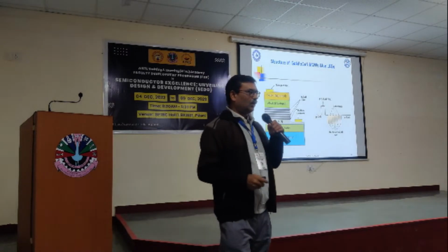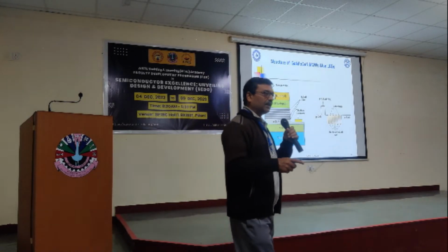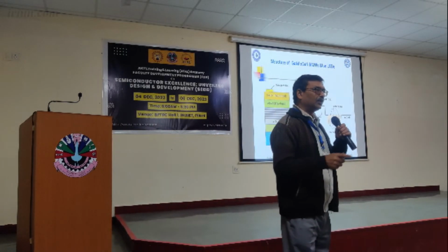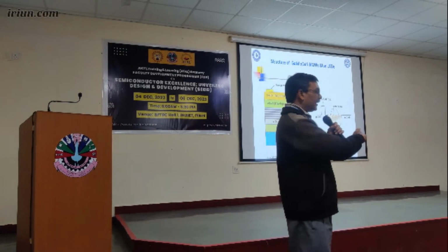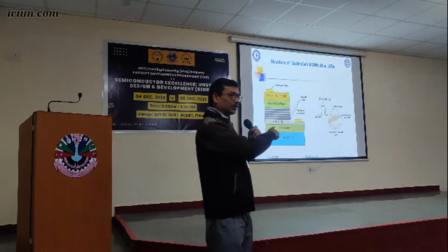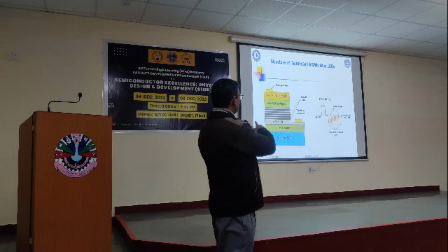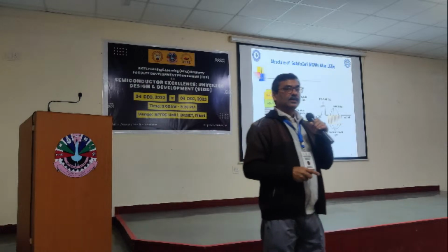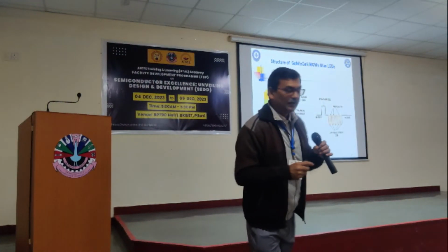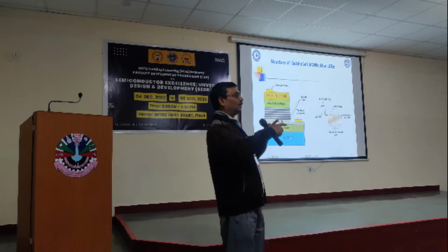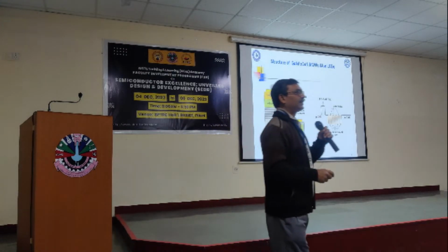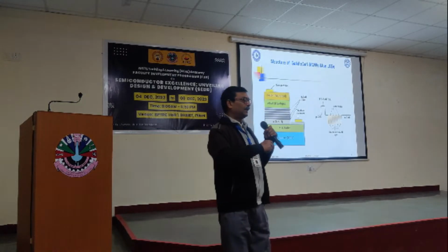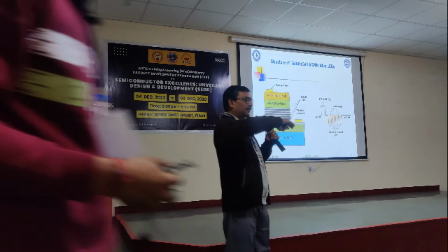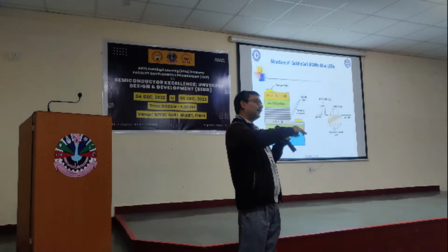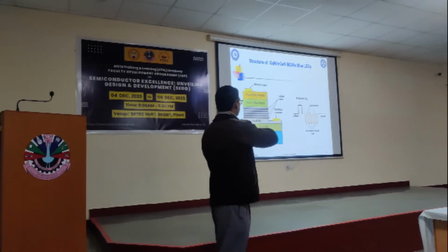So depending on the structure of that material and the growth of that, we can consider which plane we are using. This is called the C plane of the sapphire substrate, and basically this is a hexagonal structure. If we check the Miller indices, as we grow on the top of that hexagonal structure, and the growth is on the top side, this is the C plane.